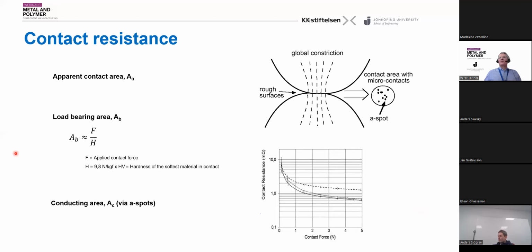And a little more on this, we have what we call A spots, where the real current is actually flowing between the two areas, which is a much smaller area than the whole contact. And if you want to increase the load bearing area, we have this relationship here. The area will grow if you increase the contact force, so you press it more together. But if the hardness of your material, the softest material in your contact, is increased, then you will decrease the area. So there's a relationship between the area, the force and the hardness of the materials.